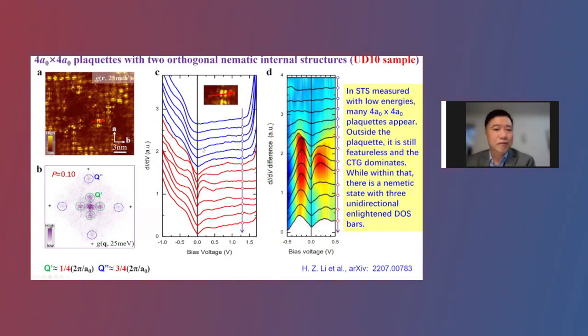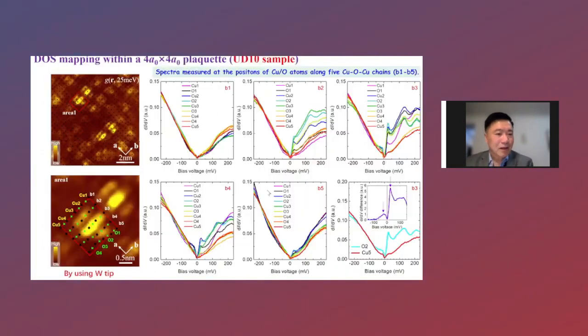So if we measure the tunneling spectrum from outside of the block to inside the block, outside the block, it shows some kind of featureless spectrum. Inside the block, you see this density of states again, by subtracting the background, okay. Let me continue. So then we pay attention to this particular block of the 4a by 4a, and we figure out the atoms of the copper and oxygen.